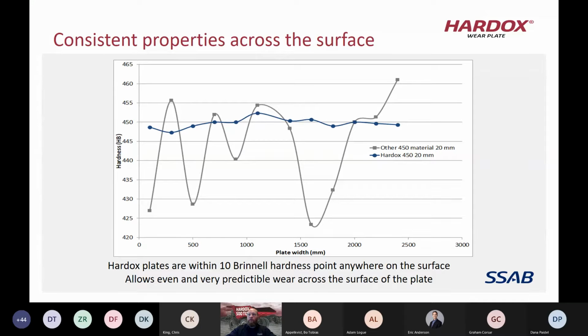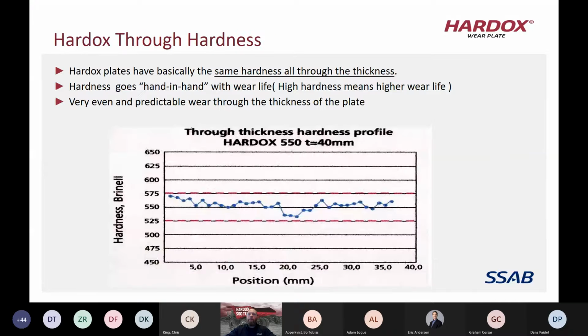So there can be a big difference throughout that plate, and that can cause uneven wear, especially in high wear applications. With Hardox, we actually guarantee that the hardness on the plate will be within 10 Brinell points anywhere across the surface of that plate. When we talk about through hardness on Hardox, we guarantee that the hardness at the center of the plate will be at least 90% of the hardness of that plate.